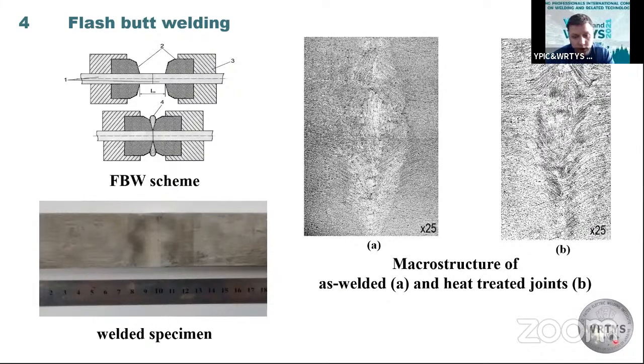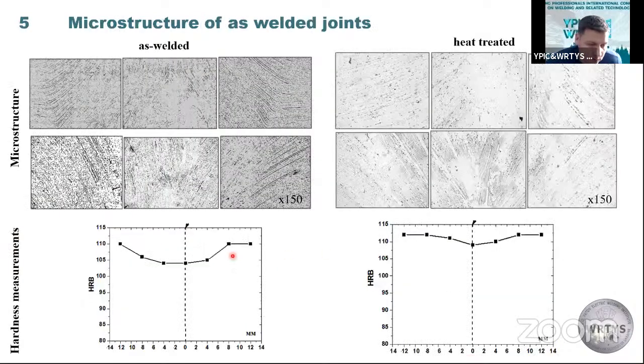Here we can see a macrostructure of as-welded and heat treated joints. Heat treated joints also have some issues in the middle of the joints. We have lower points in the hardness, but after the heat treatment, it gets much better, and we obtain a microstructure more suitable for fatigue behavior.